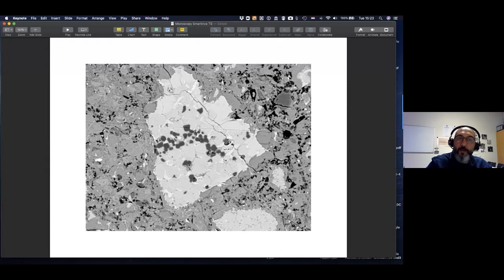You see, with optical microscope, this wasn't possible. It was impossible. I could see the total intensity because of the amount of capillary pores, but with electron microscope, you can easily see even the very details of it, which helps us to take this photo, go to our image processing software, and calculate the amount of pores, for instance, or any other phases.